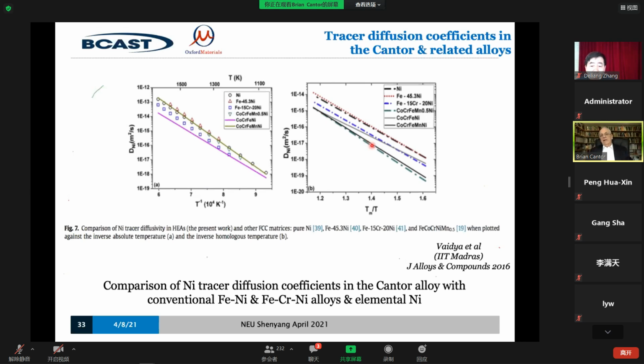So initially, Tsai et al. thought that the diffusion effect, the slowing down of diffusion, was very large. Then some people came along, did experiments and said, well, it's not that large. And finally, Vaidya et al. sorted it all out by doing tracer diffusion, which is what you need to do to get good diffusion results.